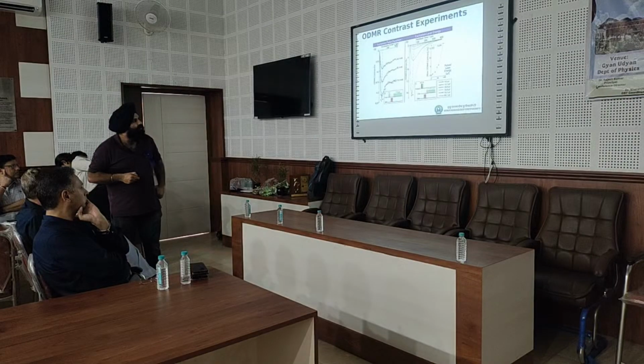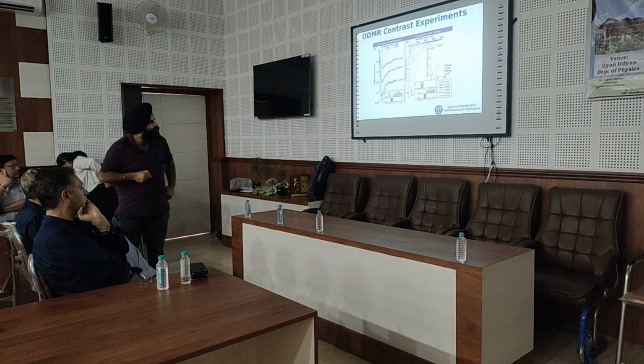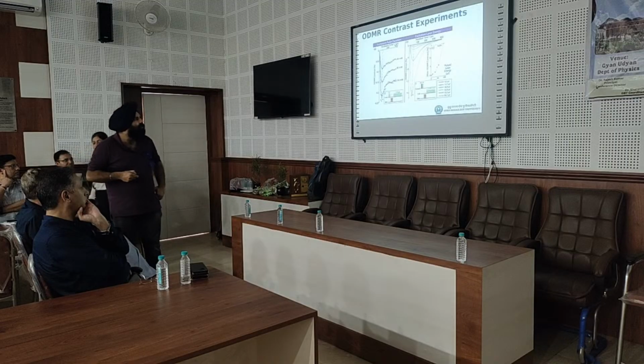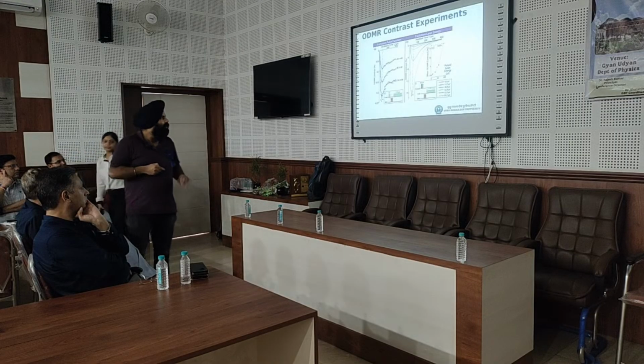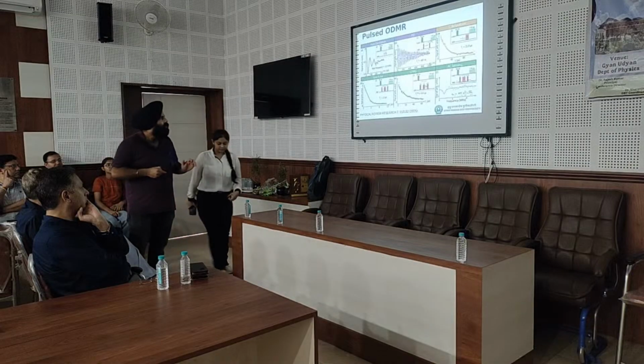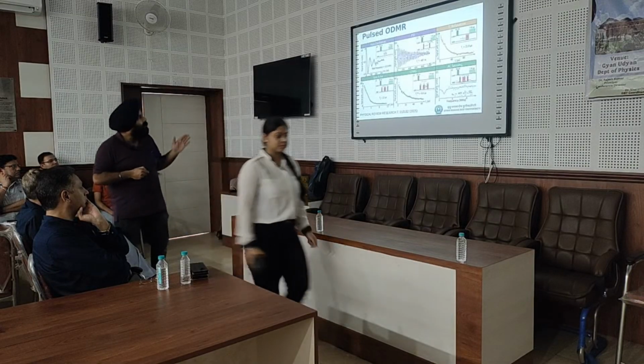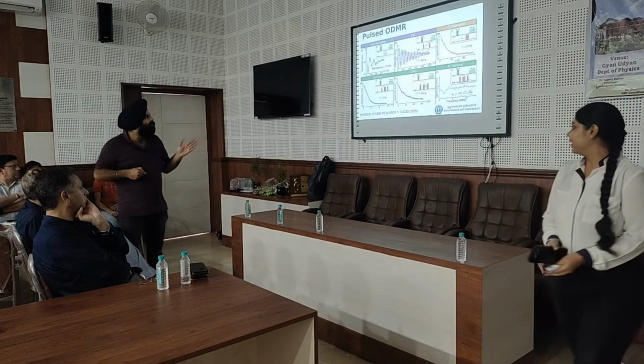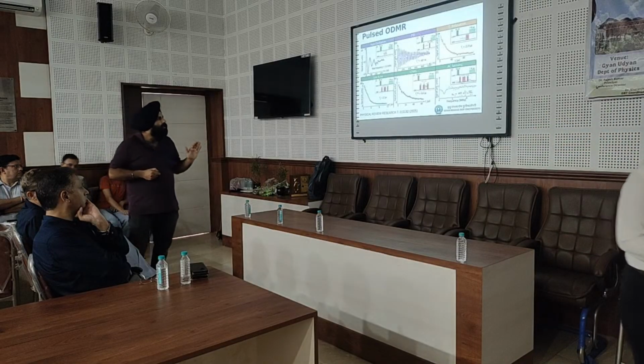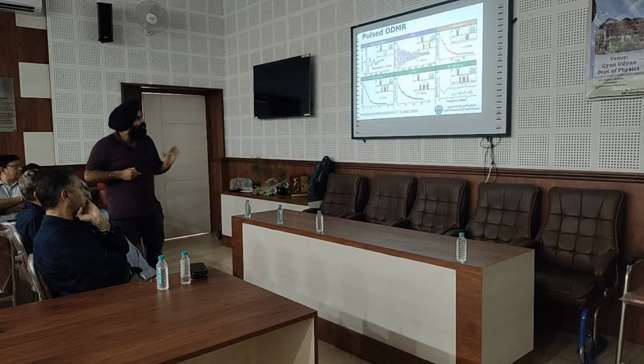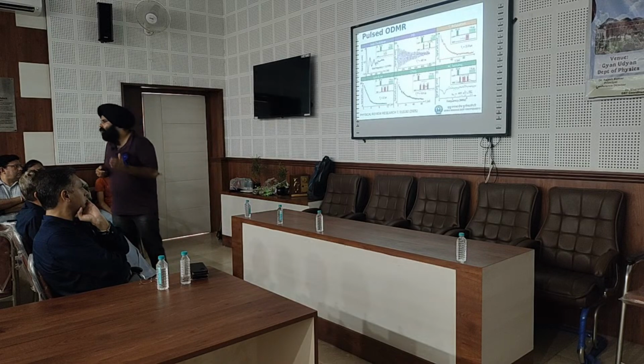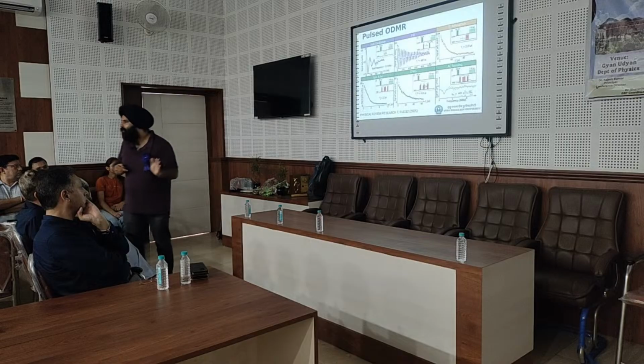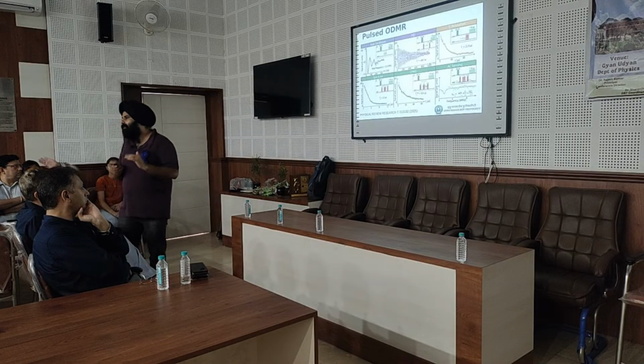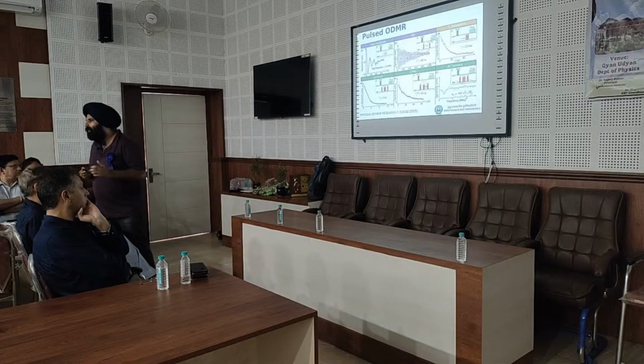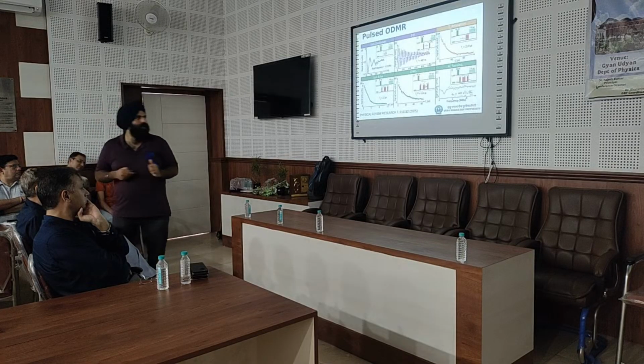I gave a 65 nanosecond pulse, and I was able to see 16% contrast, which is huge. Okay, and we certainly expected that based on this. I measured Rabi oscillation, FID, T1, and all this characterization, and based on that I estimated the sensitivity goes to nanotesla, like 4 nanotesla we can measure with this kind of sensor, which is a very nice number. My setup is not so optimized, but still we can really measure nanotesla sensitivity. So this was a great result.